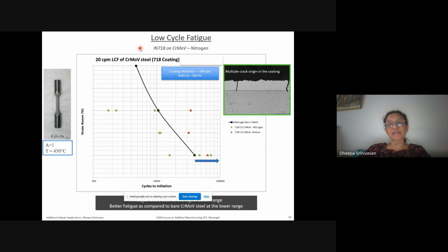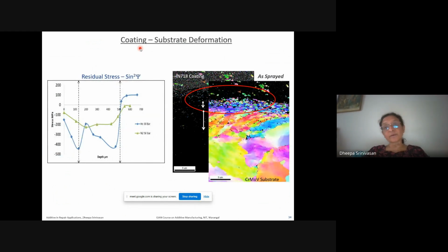So again, this is another big challenge, and it is necessary to develop test techniques that are commensurate with near net shape additive manufacturing, as I had already indicated during the laser powder bed fusion and hybrid manufacturing discussion. Then, another challenge that I wanted to show you: the left-hand curve shows the residual stresses through the thickness of the Inconel 718 coating on chromoly. But one of the challenges we face is also the fact that in very heavy, high density structural materials like nickel, cobalt, and all.